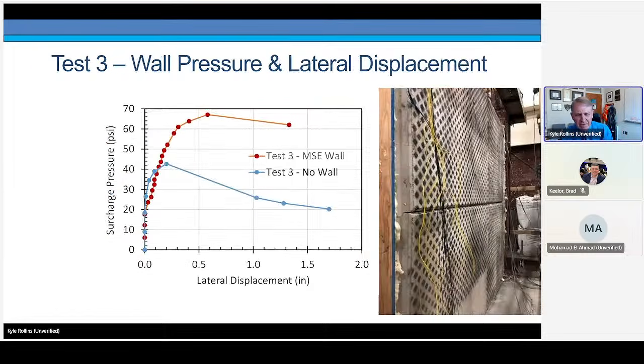Let's look now at the surcharge pressure versus lateral displacement. This is sometimes a more critical issue, but both axial and lateral are important. Once again, fairly similar behavior. We start to deform a little more. There's a break in the curve at about 20 PSI. At 43 PSI, we hit peak, we get a drop off in strength, and the displacement goes up to over 1.5 inches. We stopped the test at this point for safety reasons because the whole wall would have collapsed catastrophically into the structures lab, and we didn't want to damage our sensors and risk hurting anybody.